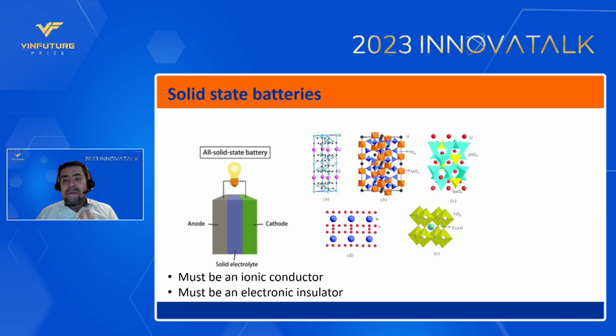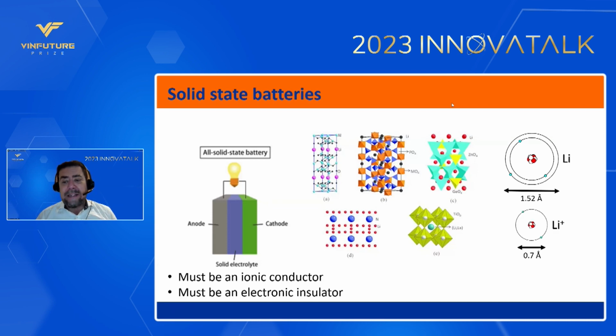So we came to this problem because we wanted to understand how an ion can move in a solid, right? So how can I make a very good ionic conductor? So think about lithium. The lithium atom is a relatively small atom. It has a diameter of 1.5 angstrom. The lithium ion is slightly smaller, 0.7 angstrom in size. And of course, this is more or less the scale of the distance between the atoms inside of a crystal. Okay, it's a few angstrom. So you might ask, how can something that size move inside of such a tight space?